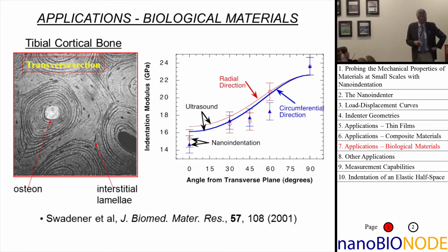And so we started a collaboration back in the mid-90s that was very fruitful and led to a lot of work in bone, in this particular case showing that the modulus of the bone is in fact a function of the angle from the transverse plane, that this material is very anisotropic, even as measured in nanoindentation, that the elastic modulus is quite anisotropic. Tragically, Jae-Young Rho, at the age of 39, died of a heart attack on New Year's Eve in 2001, I think, and it was a great loss to the community, because that guy was really bright.